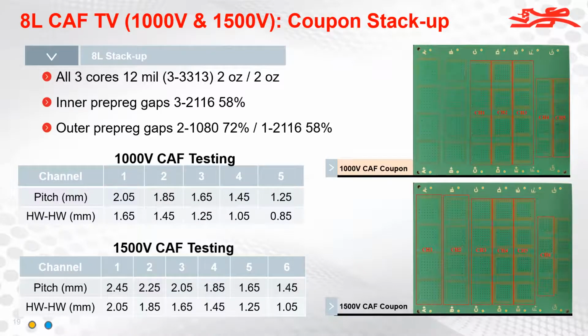Yeah, you're right about that. Those types of tests that are in the IPC, or even some of the common industry testing, like the HDP user group testing, are typically at voltages of 100 volts or less. In addition, they're really straight hole wall to hole wall gap evaluations, where the concern here with these very high voltages is not necessarily hole wall to hole wall. They are Z-axis CAF failures.